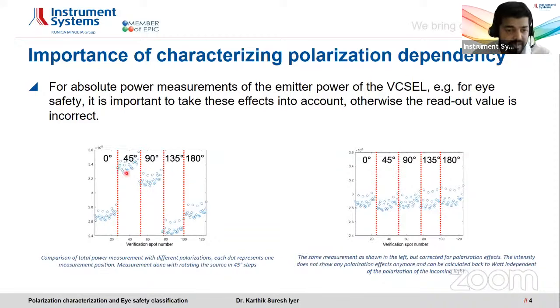Here, I would like to show you a quick example on the left. It's a comparison of the total power measurement with different polarizations, with each of these dots representing one measurement. What we did was we had a linear light source and we rotated it in 45 degree steps. And as you can clearly see, in the sum of the pixel counts there is a variation of at least 10%. So how do we correct this polarization dependency?